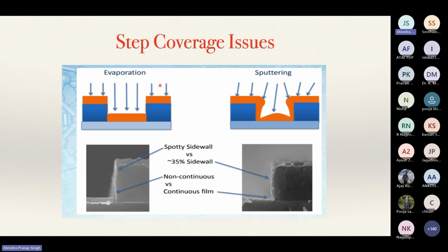Then what happens in the case of thermal vapor deposition? We always have a problem here, and the problem is the coverage. We always get some kind of spotty sidewall or non-continuous film formation here, because if this is a very sharp boundary, this side will not get deposited. So this is one of the advantages, sometimes it is a disadvantage also. You won't get a continuous film. If I am talking about a contact, in this process there is a chance that you will get high resistance here, because there might not be any deposition on the sidewall.